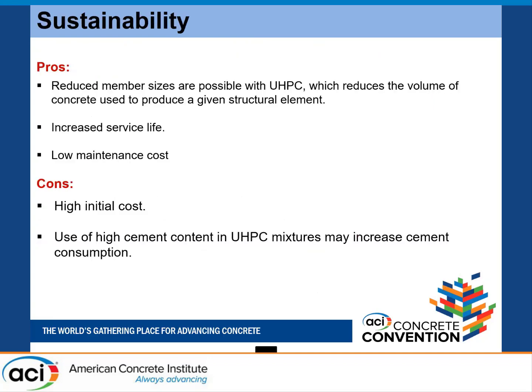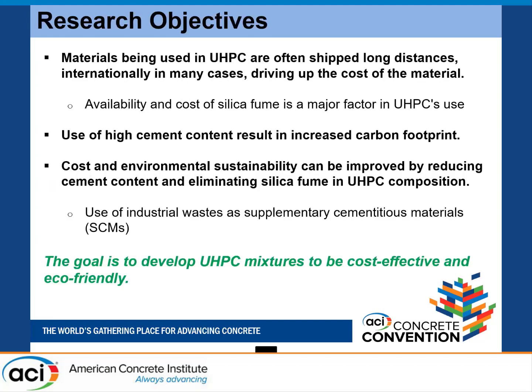Of course, I already talked about advantages and disadvantages. The main thing is high initial cost. All the researchers working on this ultra high performance concrete are basically working towards the reduction of the cost. High cement content is another issue, especially from the environmental sustainability point of view. And for this particular material, some of the raw materials such as silica fume and steel fibers are being shipped from abroad. Sometimes they have to be imported.